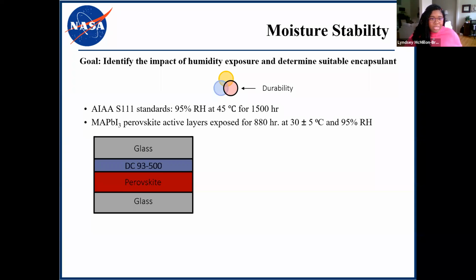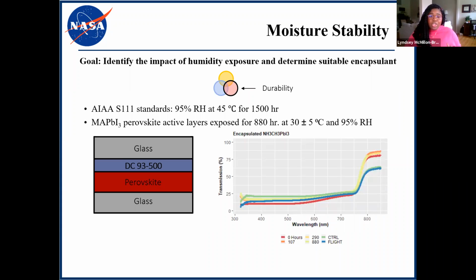So we took a perovskite methylammonium lead iodide active layer and encapsulated it in DC-93-500. And here I show a series of transmission spectra over time for these perovskite films that were encapsulated. We started at time equals 0, as made, and then subsequently measured periodically after they were exposed to an environmental chamber, 30 degrees C and 95% relative humidity, up to 880 hours.